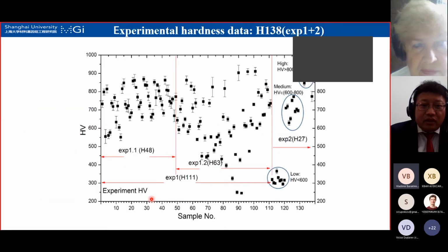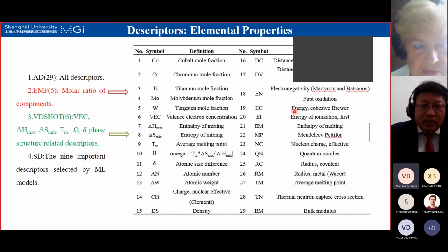We generate data first, and then we do several rounds. First, we measure the hardness of the alloy as the target. In the first round, the hardness values are pretty high. In the second round, we generate alloys with low or medium hardness, because we want data variety. Those are important for building a good model. And then we predict new ones, and we do the experimental verification, etc.